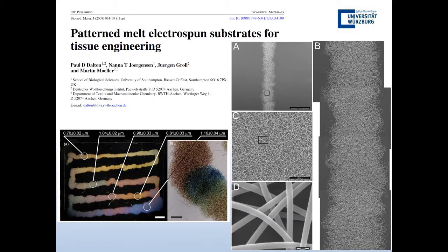And so forth. We were able to start direct writing, and actually this is not done with an automated collector, it's done by hand. I actually stole an axis collector off a microscope on the weekend, unscrewed everything, put it underneath the electrospinner, and did this writing by hand, but you get beautiful fibers, and they were actually coloured depending on the diameter as well. And these were blends of these block copolymers and also PCL.